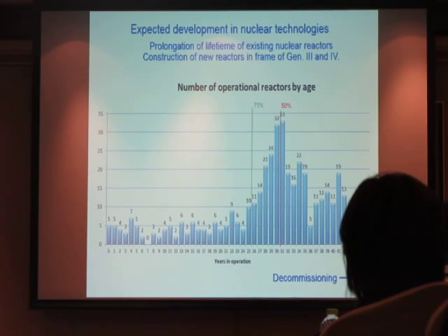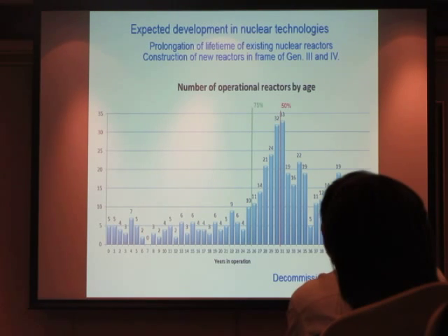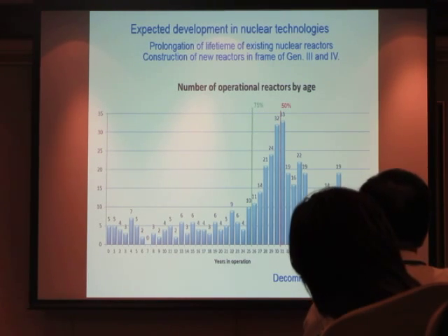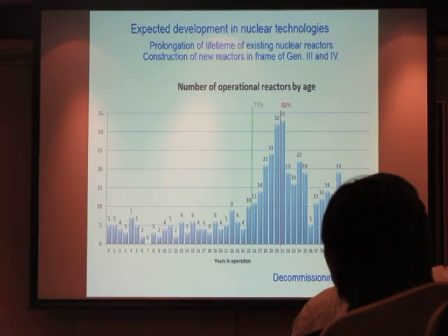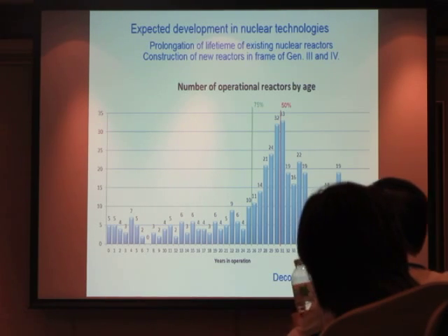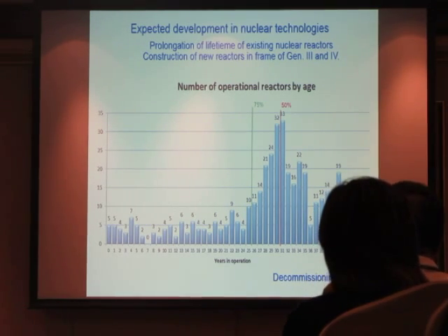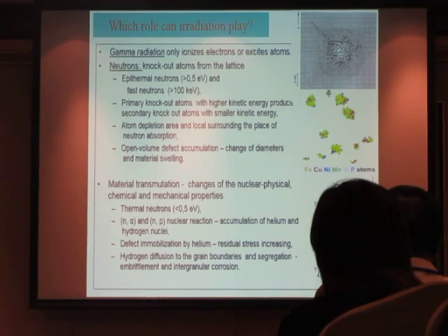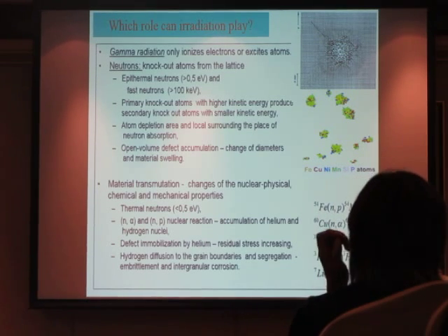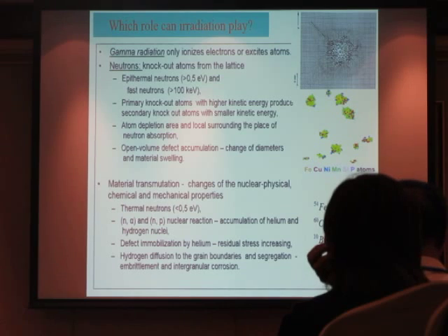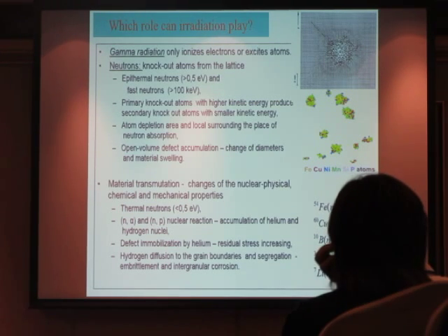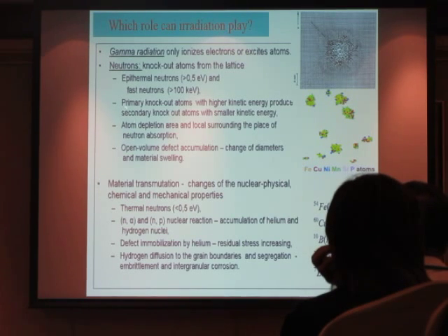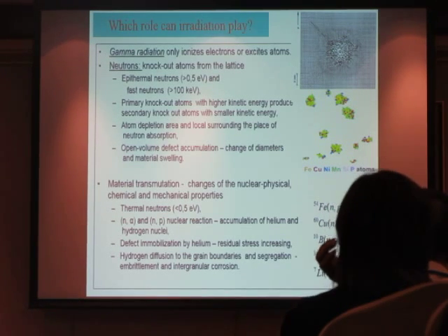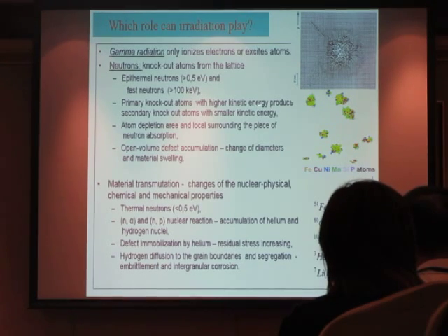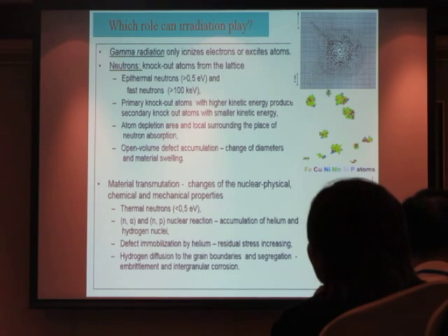Aging. We have actually more than 430 reactors in the world in operation, but 50% of them are older than 30 years. If we will not prolong the lifetime, they will be shut down. There are many effects from irradiation, and how to know about the changes from the irradiation. We focus mostly on the neutron knockout atoms from the lattice, because gamma radiation, electron radiation, and other types cause small changes, but not such large defects.